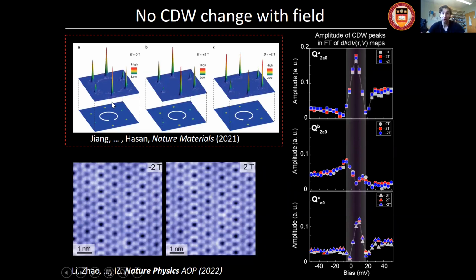They report that the CDW state is chiral based on slight differences between different CDW peaks. And then, once you flip the field once, some of these peaks change a little bit. They looked at the topograph primarily, and this was their finding. So the CDW is chiral with this magnetic field dependence, which is not the case based on our measurement, when we carefully image the same area of the sample with the same STM tip over and over again. And our conclusions are now corroborated by at least 2 or 3 other groups that looked at this as well.